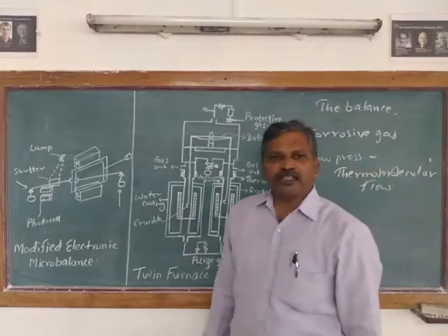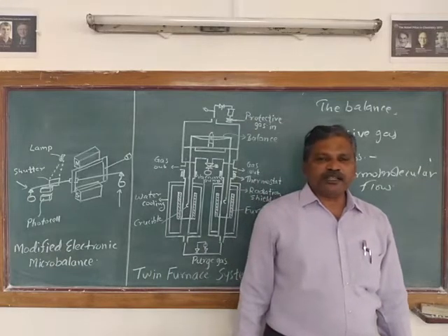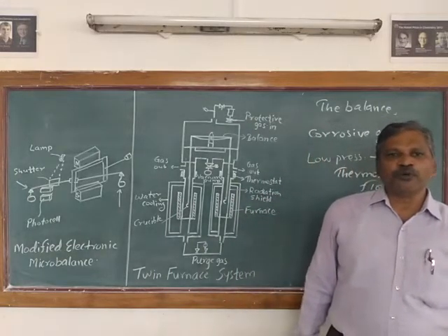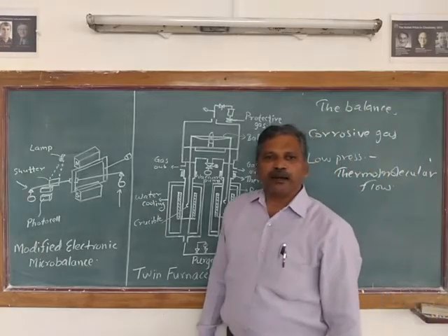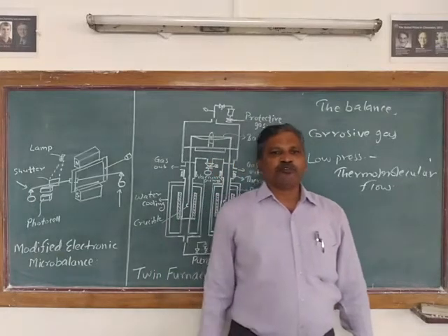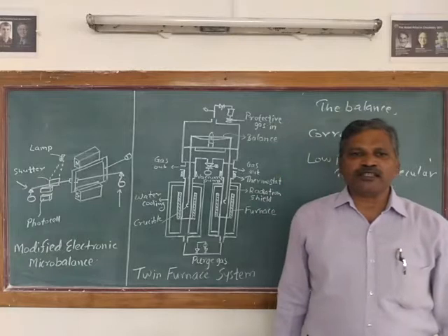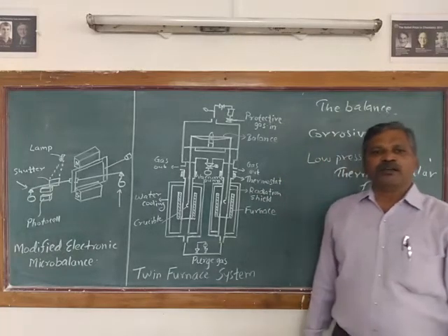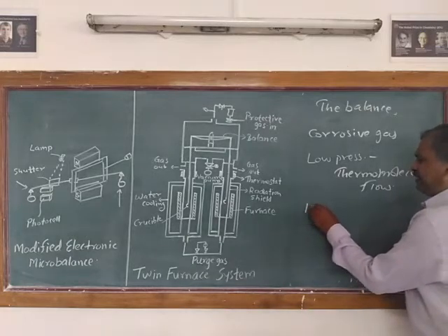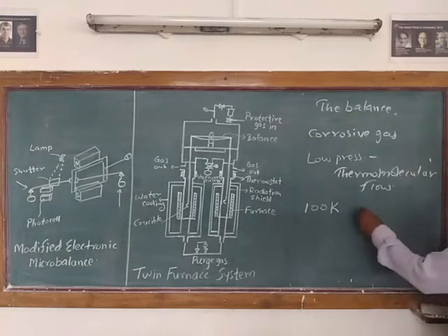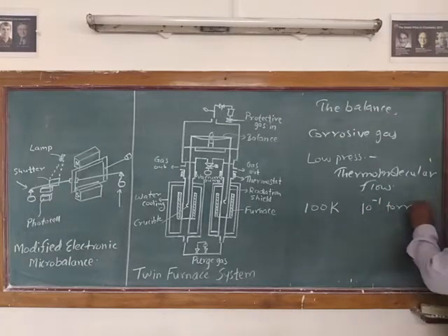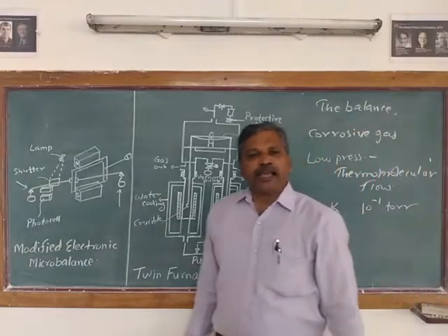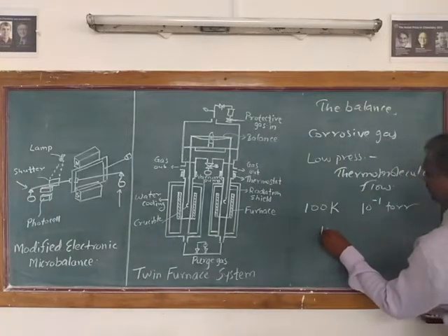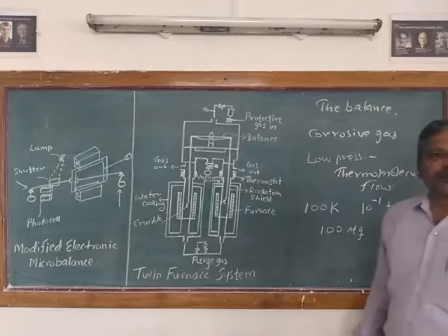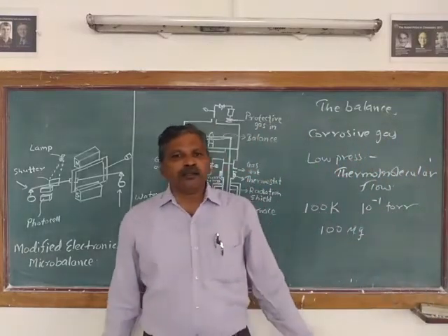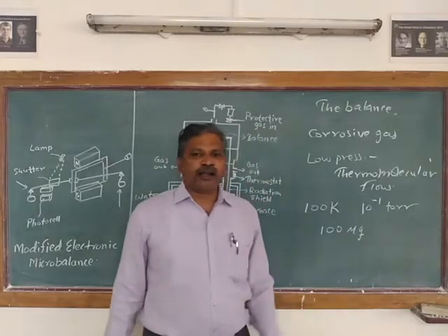If the sample or its suspensions or counterpoise experiences the temperature gradient when the pressure is low and the mean free path is comparable to the dimensions of the apparatus, the flow of gas molecules can cause an apparent weight change. For example, if there is a temperature difference of 100 Kelvin and a pressure of 10 raised to minus 1 torr, then the effect can be as much as 100 microgram. So there may be a change in the weight of the sample of up to 100 microgram.